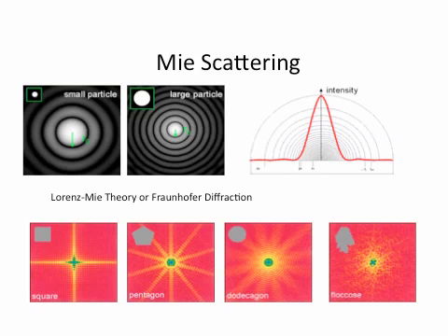Then from that scattering profile, in the machine that you use, typically for small particles you can use either dynamic or static light scattering, and for larger particles you use equipment like a Mastersizer from Malvern. In the equipment there are mathematical procedures to calculate this back to a size. But in order to do that, you need to know a little bit about the shape of these particles to get the number right.